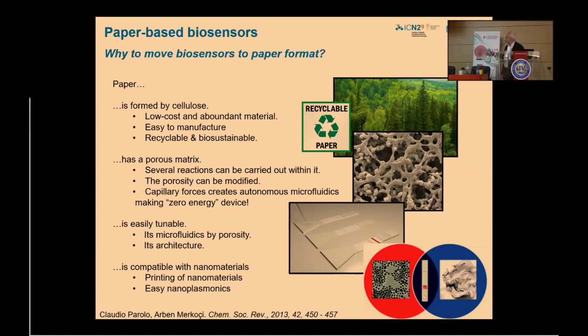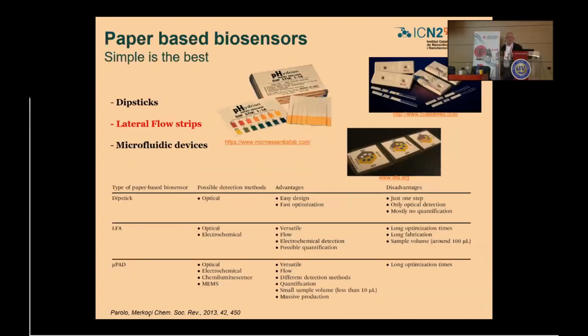The fact that we have this porous matrix can induce moving of the liquids by capillarity, so you don't need a pumping system. So you just put the sample and the sample will move, but you should find a way how to move it. Of course, by simple cutting of the paper, you see here different shapes. We can tune also the microfluidics. I'll show you why and how we achieve this. And finally, in the paper, we can integrate nanomaterial and we can convert a piece of paper to a plasmonic paper, a fluorescent paper.